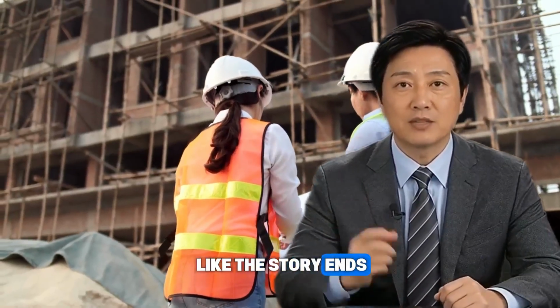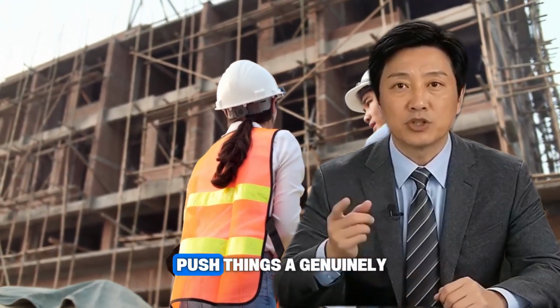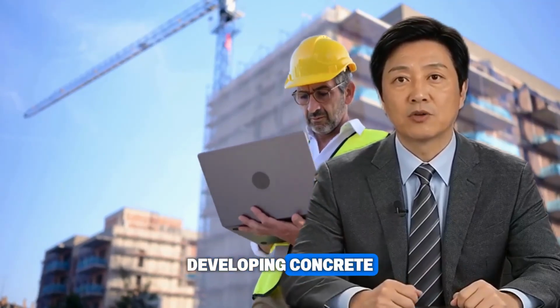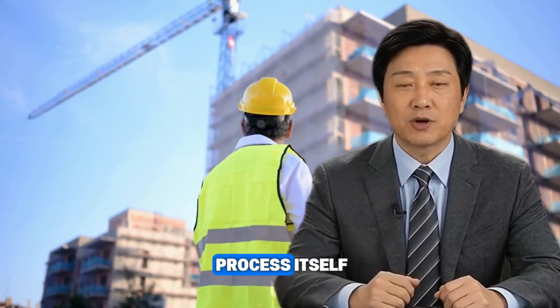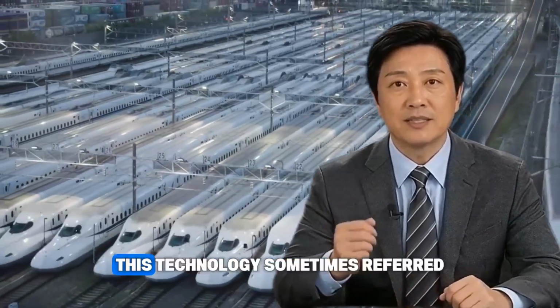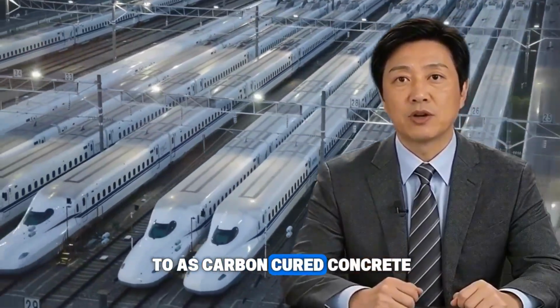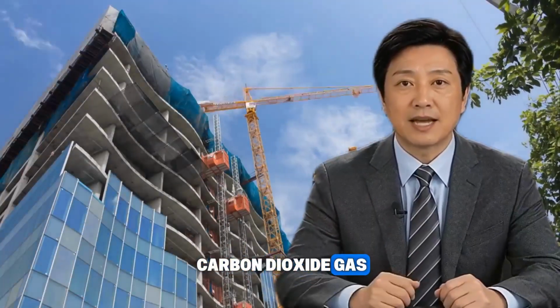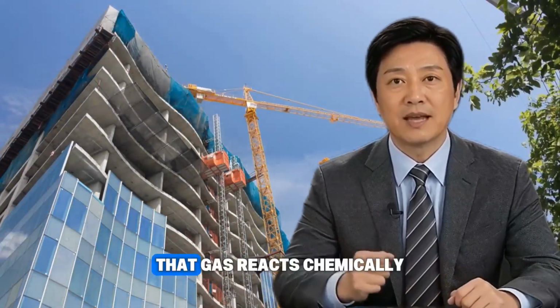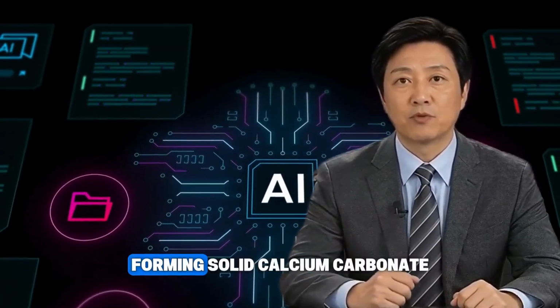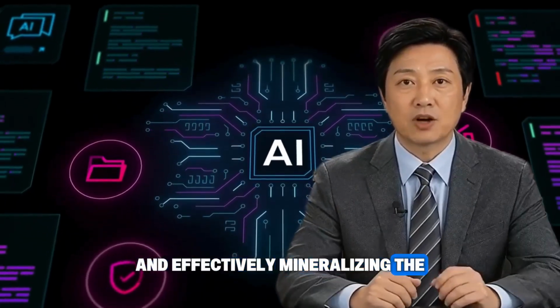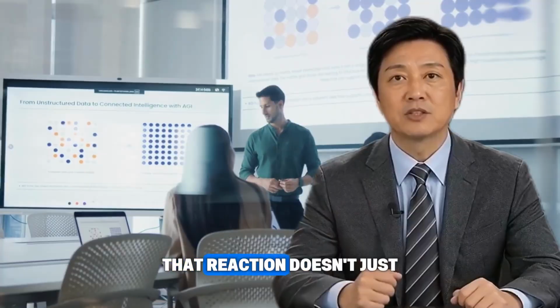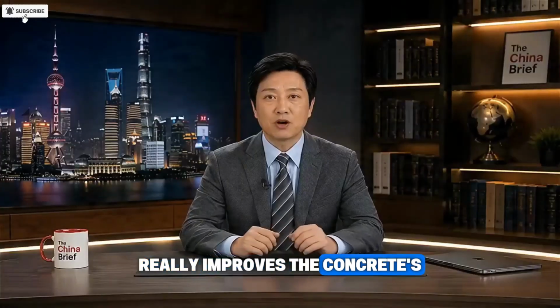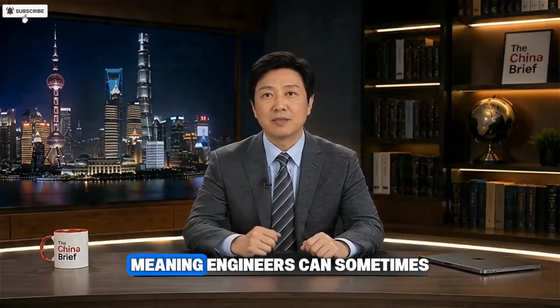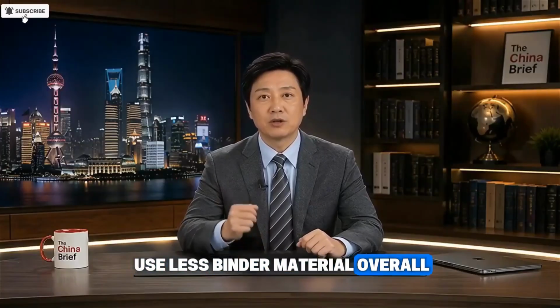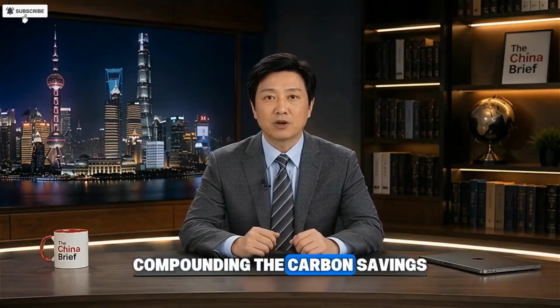Just when it seems like the story ends with eliminating emissions, some Chinese research teams push things a genuinely bold step further, developing concrete that actively absorbs carbon dioxide during the curing process itself, rather than simply avoiding emissions up front. This technology, sometimes referred to as carbon-cured concrete, works by injecting captured carbon dioxide gas directly into the concrete mixture while it's still curing. That gas reacts chemically with calcium compounds in the mix, forming solid calcium carbonate and effectively mineralizing the carbon dioxide permanently into the concrete structure. That reaction doesn't just neutralize emissions, it actually improves the concrete's compressive strength and density in the process, meaning engineers can sometimes use less binder material overall to hit the same structural performance targets, compounding the carbon savings even further.